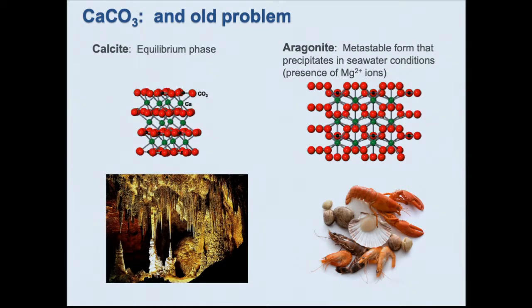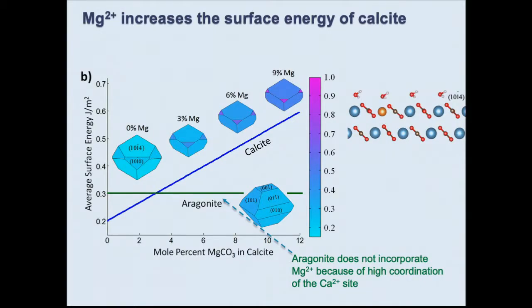And it's been known empirically that this is highly correlated to the magnesium content in seawater. Because it's actually to the point where the magnesium content in seawater has historically fluctuated over hundreds of thousands of years. And when it's below a certain point, you actually don't form aragonite in the oceans. And again, that's a surface energy problem. So what happens is in aragonite, calcium is highly coordinated by oxygen, and magnesium does not want to substitute in there. So magnesium has essentially no effect on the surface energy of aragonite. But magnesium does substitute into calcite, because in calcite, calcium is 6-fold coordinated, which magnesium can go into. And magnesium actually increases the surface energy of calcite.